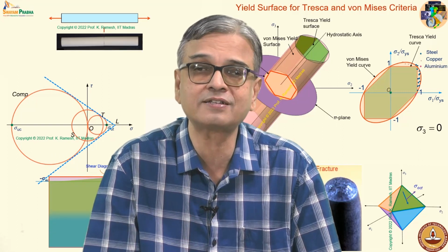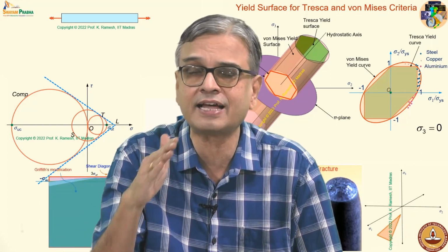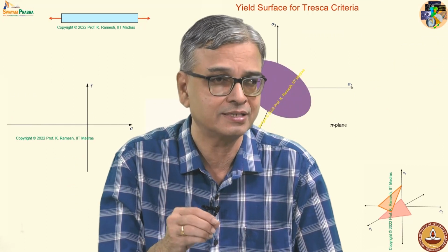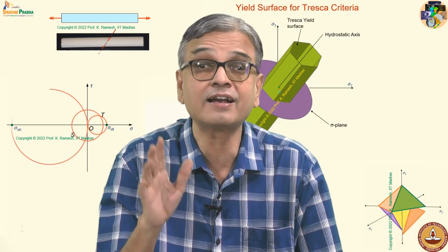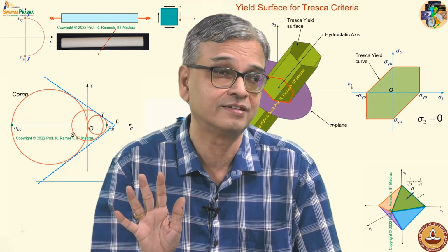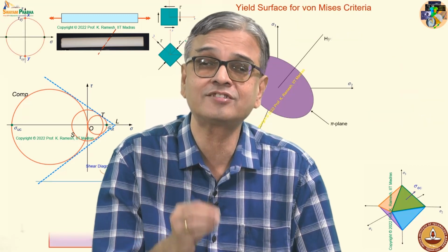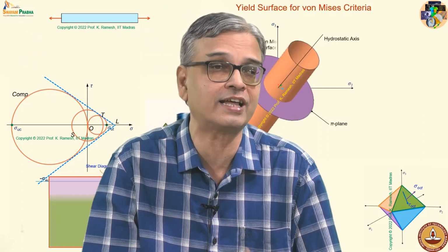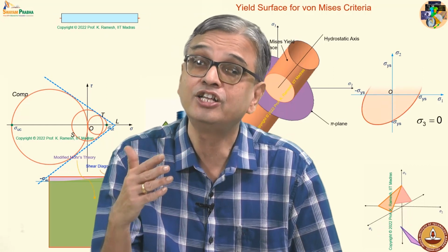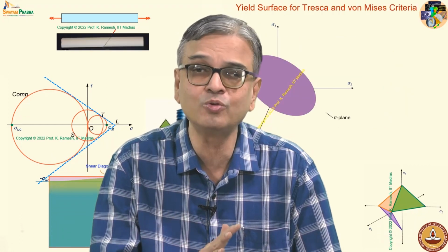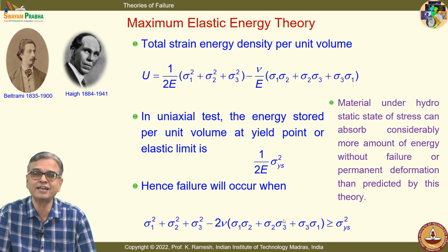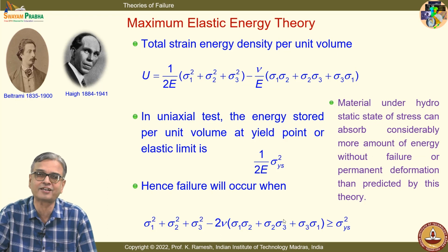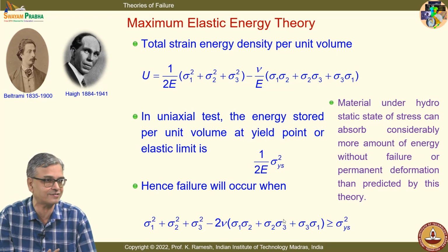So, one idea people suggested is you cover this material with a thin metallic cover, metallic sheet, so that the liquid does not get into the crevices. Even glass has withstood very high hydrostatic stress. So, this is the reason people thought your elastic strain energy is not the right index for failure analysis. You have to look at the distortional energy. Is the idea clear? You have to move and see distortional energy, because the experiments do not support the predictions. The theory simply says, instead of looking at 10 different things, look at the elastic strain energy, see what happens in a tension test. That is how people have coined different theories.